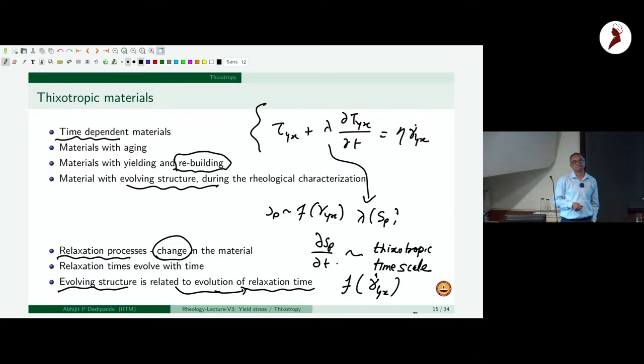No, that is where the confusion is. In one case you increase the shear rate and you observe some behavior, but this is with respect to time, at constant shear rate. So what I'm saying is, when you start shearing the system, by the way, 90 to 95%, a very high number of materials, do decrease in viscosity at constant shear rate. There are very small classes of materials where the opposite is observed, where the viscosity increases at a constant strain rate with respect to time. And there mechanisms such as clustering due to shearing would start happening. But it's a very small class of materials.